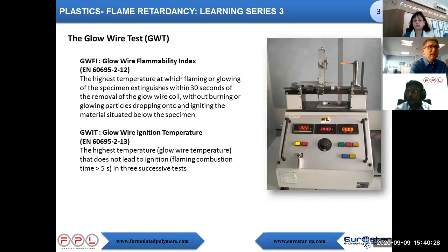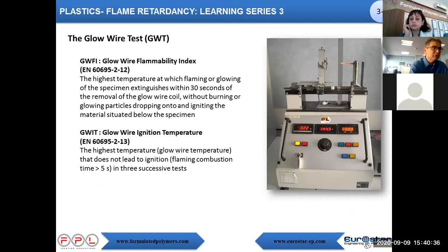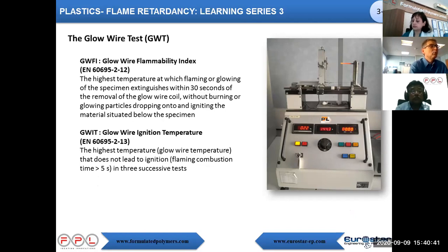Then basically, the glow wire test has two different families of tests you can conduct, measuring two different things. The glow wire flammability index, so-called GWFI, is a test where you apply this wire against the plastics for 30 seconds and you see the reaction of the plastics: if it goes on burning, if it stops burning, if it propagates the flame.